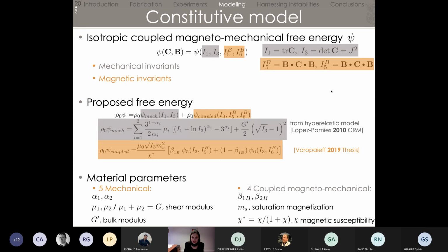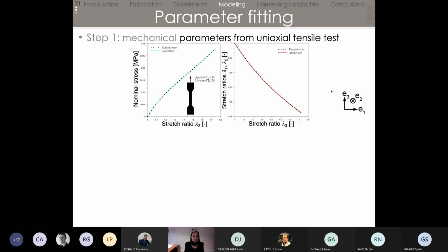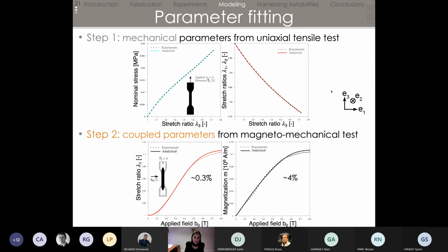So for identification, we simply take our results. To identify the mechanical parameters, we simply use the stress-stretch curve and identify that fairly simply, which is something classic for elastomers. Now for the magneto-mechanical test, we identify the parameters on 2 curves. The one that gives you magnetostriction as a function of the applied field on the left, where you see already that you don't get a perfect match as you're doing the identification. And we also get some parameters from the magnetization curve, again not perfectly, even at the identification stage.